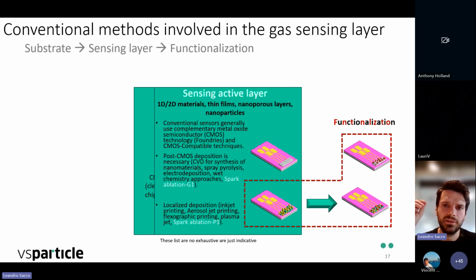So we cannot really select the area where we want to print. And that could be a very interesting feature regarding gas sensors, because with gas sensors, sometimes we want to make arrays. And sometimes we need to functionalize different sensors on the same platform. So localized deposition techniques, like inkjet printing or aerosol jet printing, are capable of this. And then spark ablation coupled with the nanoprinter can also do this. What is very important to highlight here is that we can not only deposit the sensing active layer, but also functionalize our device.